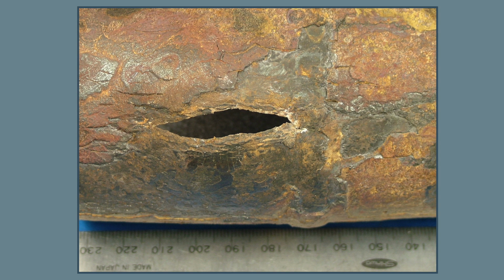It appears like a burst pipe, and it probably is. It's actually a pipe from a boiler. So boilers basically work at high temperature. We're looking at 300 degrees Celsius. Okay. Most of these tubes are made of carbon steel. They've got good strength, and we do quite a lot of investigations on boiler failures.